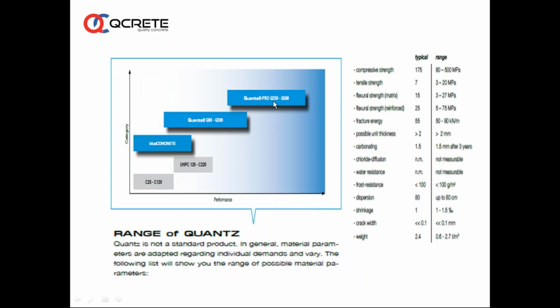So here the high performance concrete, what they're talking about is 250 to 500 MPa is possible, and you can see here the normal range, and then they can go up to this kind of strengths actually, tensile strengths, flexural strengths. You can make highly durable tile-like structures.